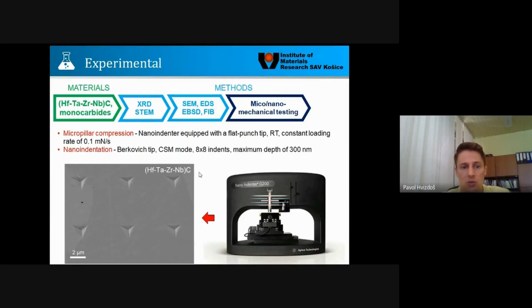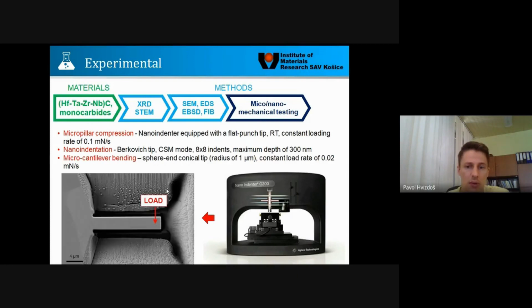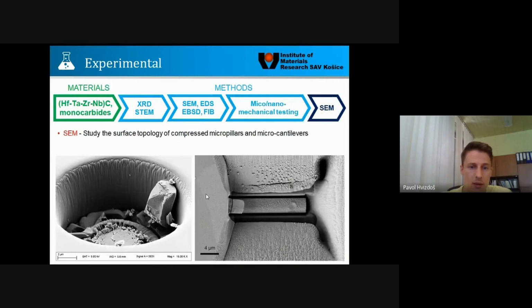Additionally, we did also nano indentation. As you can see, it was basically a very shallow nano indentation using a maximum depth of 300 nanometers using a Berkovich tip. And as I mentioned at the beginning, as we fabricated microcantilevers, those microcantilevers were fabricated with the aim to compress them using a sphere and conical tip and record the fracture properties. And finally, all the fractured or compressed or deformed materials were observed, examined by SEM.